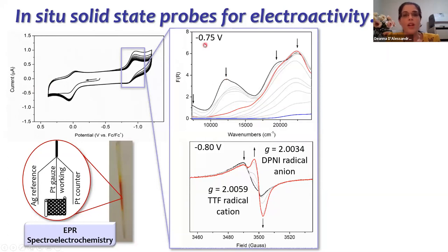So as soon as we apply a reductive potential, this collapses, but we can regenerate the starting state. And in fact, we can do the same experiment, the solid state spectroelectrochemistry, with EPR, or electron paramagnetic resonance, as well. And we see here in the black curve two overlapping radical signals from the TTF radical cation and the naphthalene diimide radical anion.